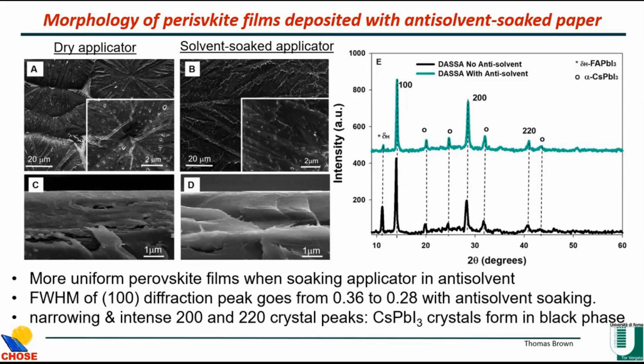We carried out XRD, and the full width at half maximum goes from 0.36 to 0.28 in the 100 direction, which means higher crystallinity for the films made with the anti-solvent-soaked applicator. And also the composition looked better because we used the bicomponent perovskite, and the black phase, which is photovoltaic active, of cesium lead triiodide, had a more intense peak.